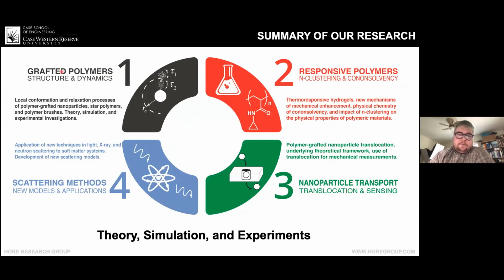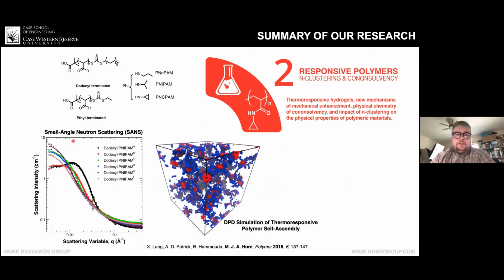And so you can see that we have four main areas that we work in. We work in grafted polymers, and we look at the structure and dynamics. We work in responsive polymers, nanoparticle transport, and also scattering methods. To give you a flavor of what that means, in terms of responsive polymers, we're interested in things like polyNIPAM and related polymers. And just as a quick example, one thing that we noticed when we synthesized these is that this end group here on the polymer, the number of carbons determined what it did in solution.